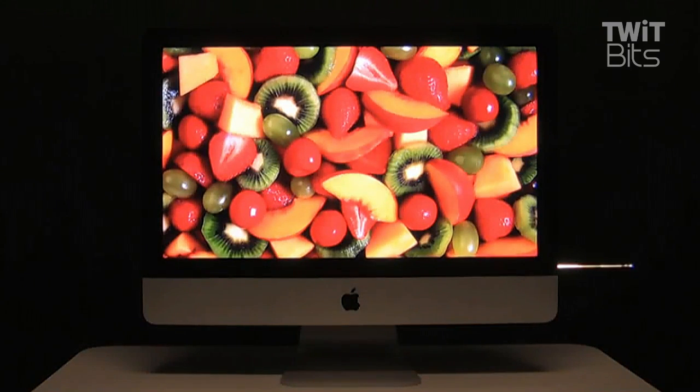In terms of the gamut. That to me is just really astonishing. It really shows beautifully that you start with a blue light source — LEDs. You put quantum dots that have been specifically engineered to emit red and green at particular wavelengths under bombardment from blue, and that blue and the red and green from the quantum dots combine, and you get a full color image. It's just really quite a nice display.